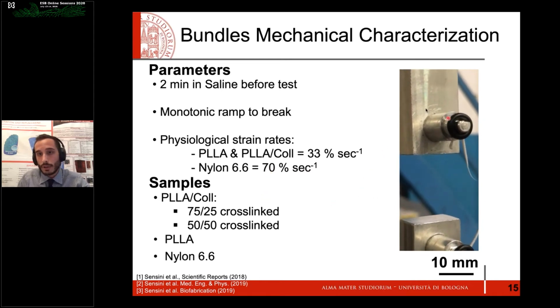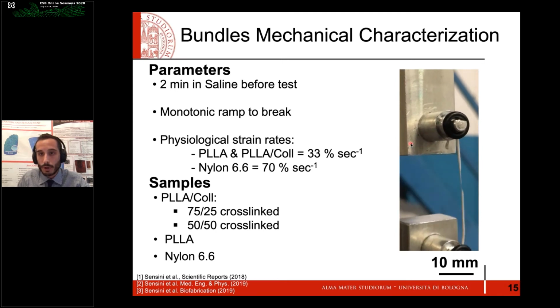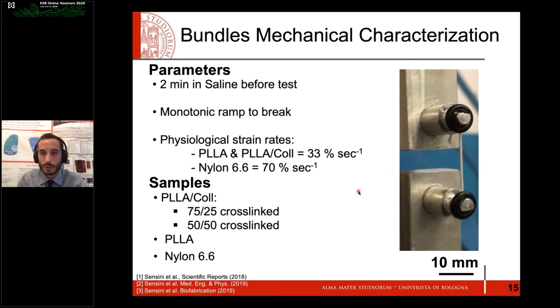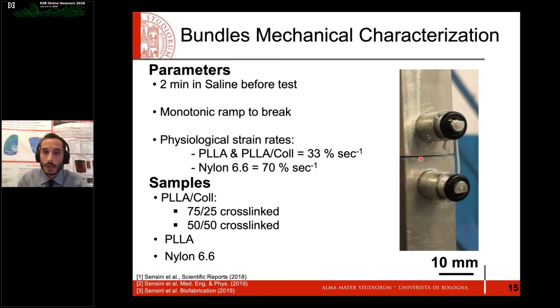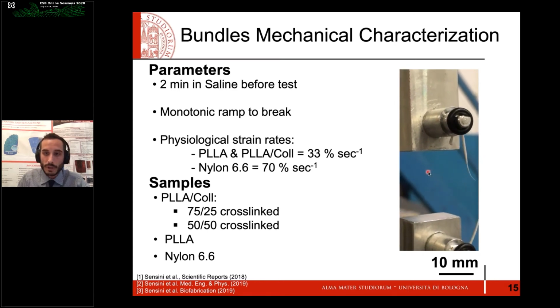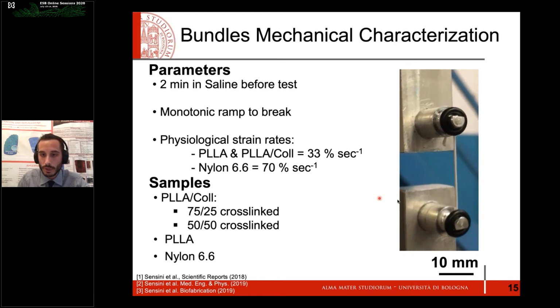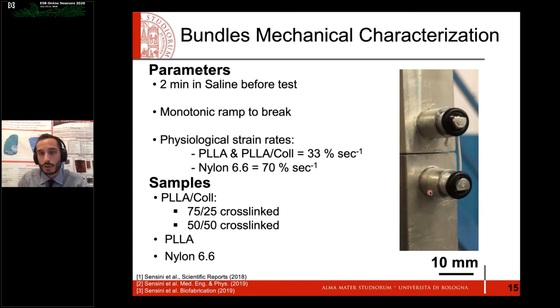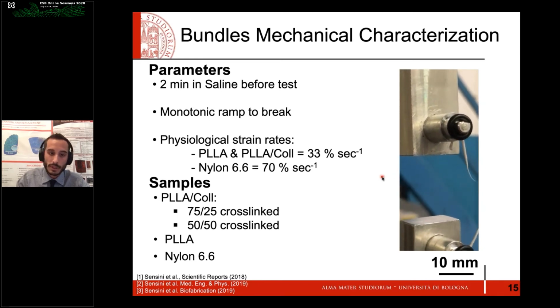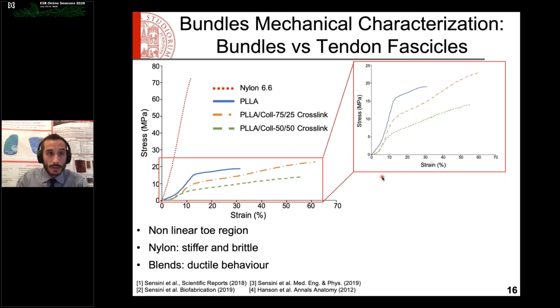Moreover, in order to reduce as much as possible the stress concentration between the bundle ends and the grip of the machine, we designed dedicated caps and grips, as shown in this slow motion video, which allowed us to reduce stress concentration and break our specimen in the middle of the gauge length.